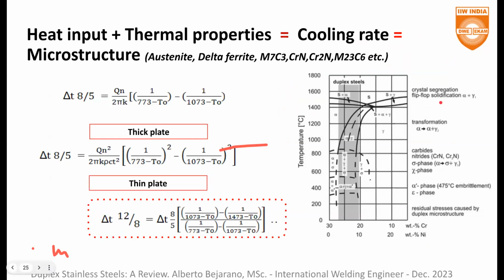Okay, so we have to heat the material to be able to melt the material, and the cooling rate must be higher than a certain value so we don't have these phases, but lower than another so we have enough austenite. So this is very, very important, okay?